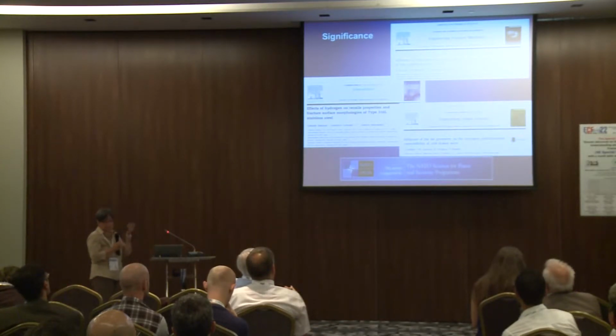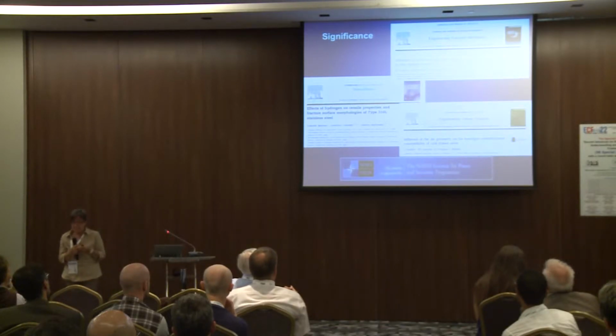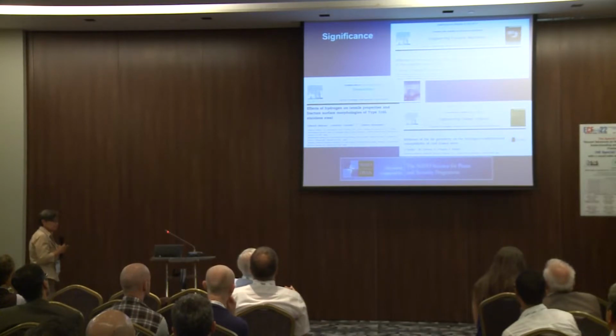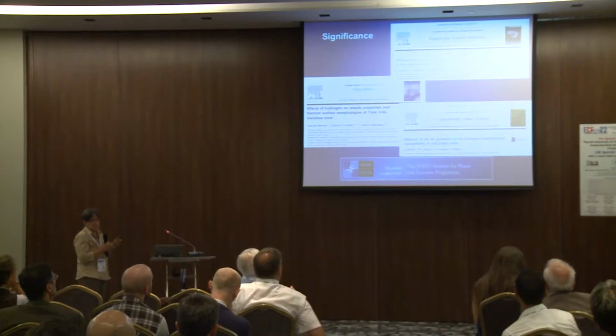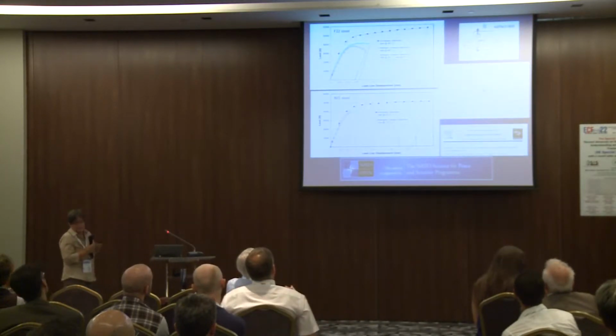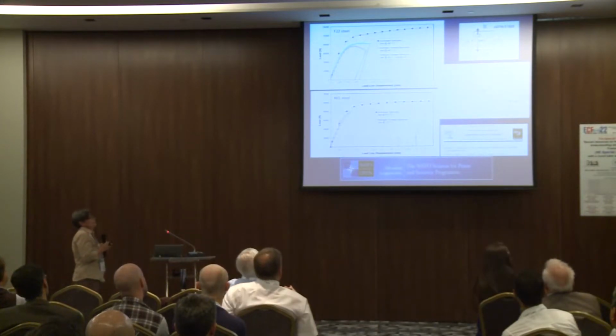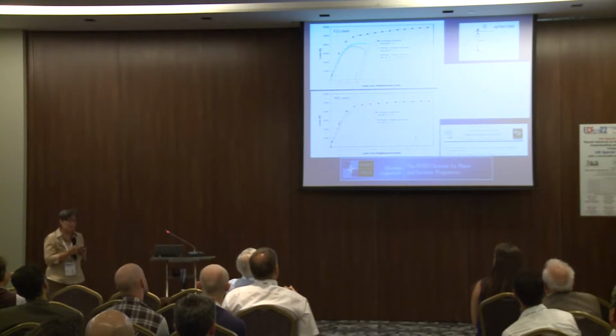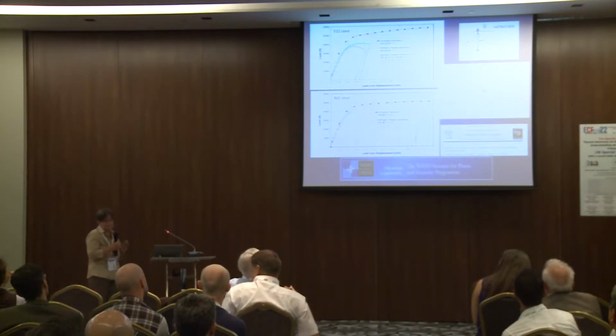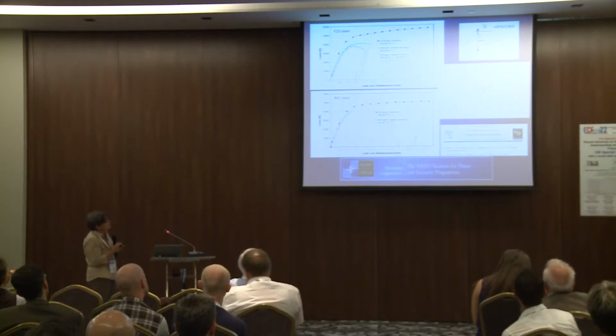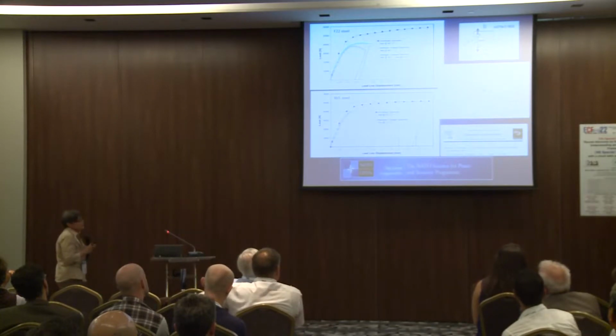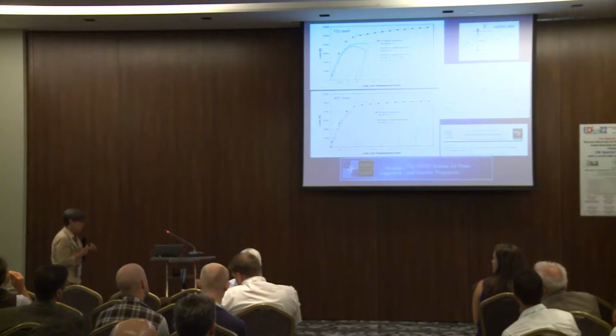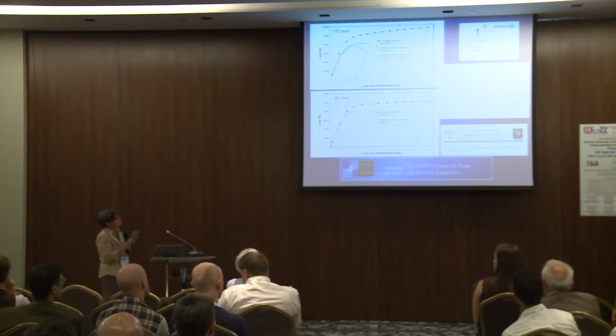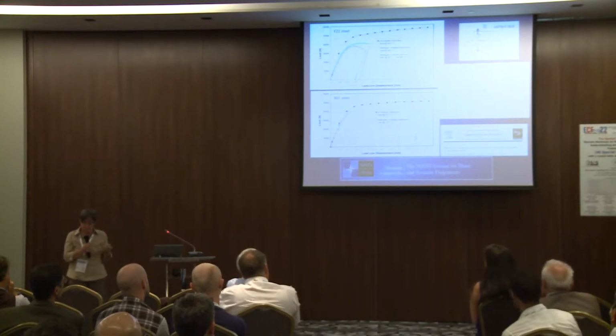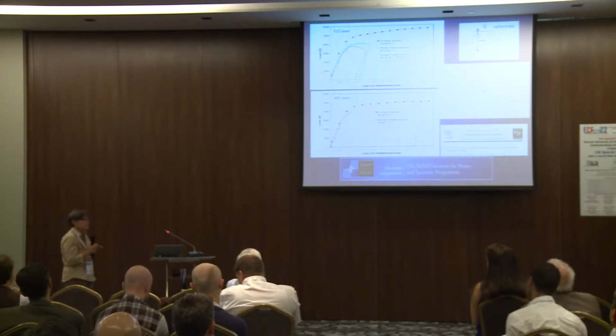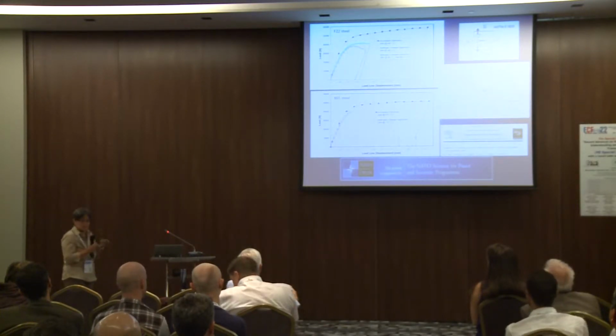If we look to the literature, and this morning I listened to results which are consistent with this, a lot of attention has been paid, especially to the embrittlement which is induced in metals by the presence of hydrogen in several applications. However, the reduction of ductility is usually accompanied also with the change of other mechanical properties, for instance, the material strength and the yield limits. These material properties can usually be inferred by techniques which may be simpler than those traditionally used for getting this sort of diagrams, which rely, as we've seen already this morning, either on compact tests or tensile specimens, which are cut and machined from the thickness of the pipe wall.